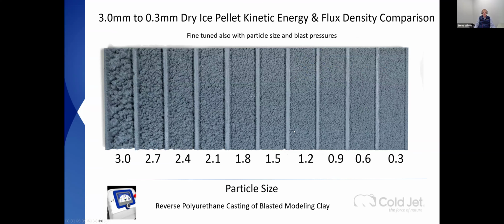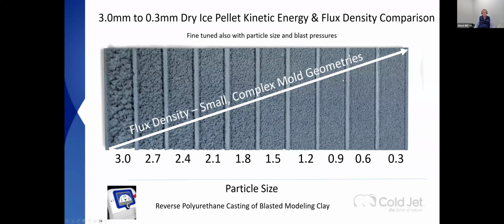If you were to look at 3 millimeter pellets versus the microparticles and particle size, we blasted on modeling clay, and you can see the impacts that they made on modeling clay, and then we poured a reverse polyurethane casting. And you can see on the left-hand side, 3 millimeter, but as you move towards 0.3, as you move up that scale, you see the flux density increases. You're getting more particle strikes per square inch than you are with 3 millimeters.